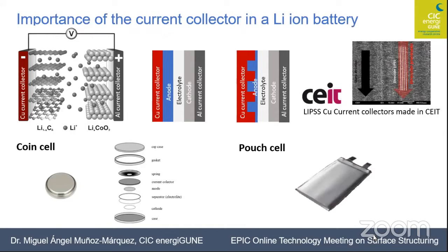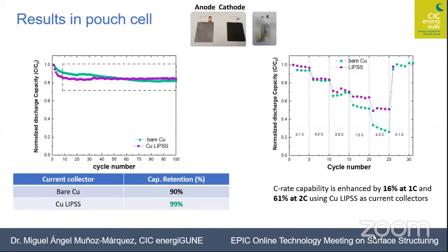which in our case has the size of a battery that you can find in mobile devices, mobile phones, for instance. So like a proof of concept that this can be done in a larger area. And essentially this is a 4 by 6 centimeters area. So we got very interesting results, very good results on the coin cell, but also on the pouch cell, and this is what I show here.